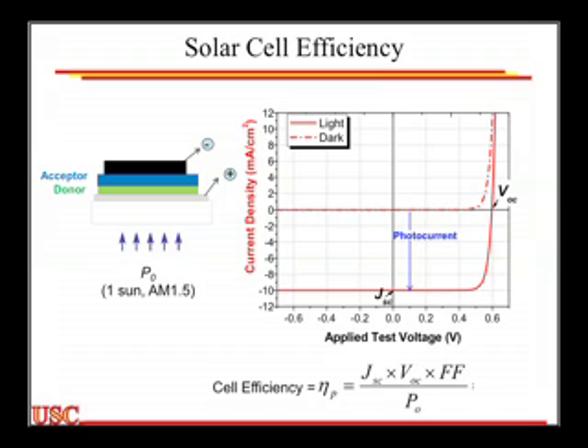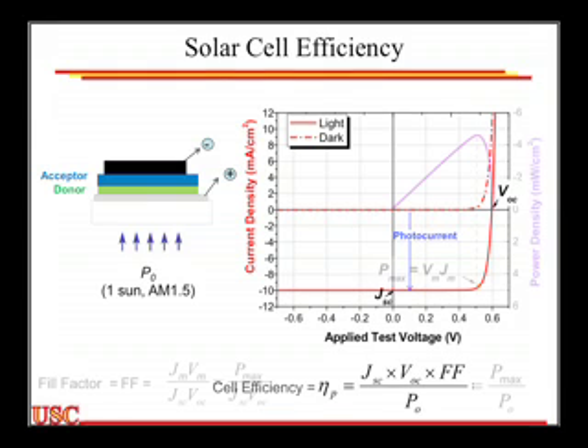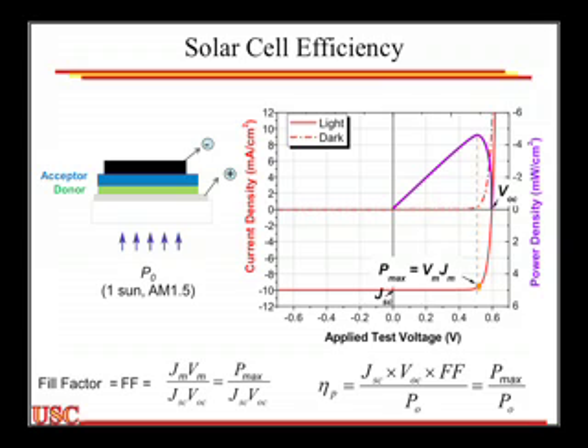That current and voltage combination that I call VM and JM, that product is Pmax. When you see the data, though, nobody talks about Pmax, and they don't talk about VM and JM. We talk about JSC, VOC, and this thing called the fill factor. Well, the fill factor actually is directly related to Pmax. You'll oftentimes see it drawn this way, where you see these two rectangles. The fill factor is simply the ratio of the maximum power rectangle, which is JM times VM, divided by the product of the short circuit current and the open circuit voltage.